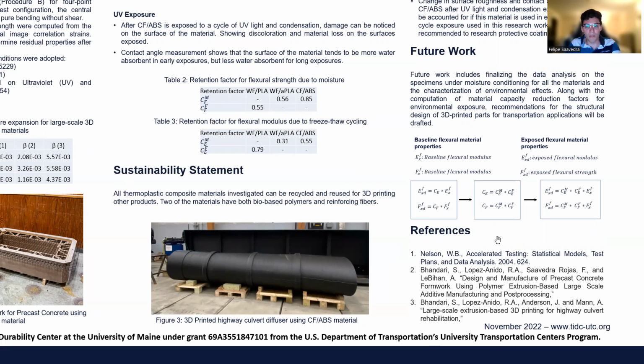Also, something I would like to mention that my research is moving towards. With my work, I was able to obtain the baseline flexural material properties. In this case, flexural modulus and flexural strength. And then we have the exposed flexural material properties. With this, we can obtain the retention factor that I mentioned before, and we can obtain these factors for each conditioning, in this case, moisture or freeze-thaw cycle. So then the exposed properties are going to be the baseline property multiplied by these factors.